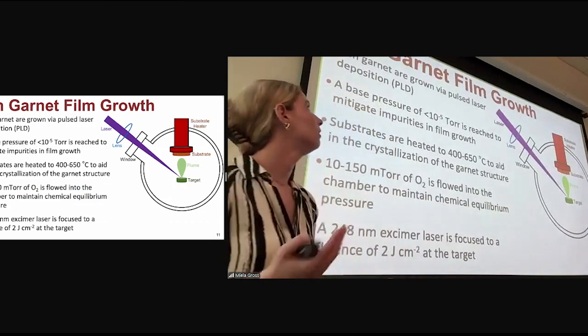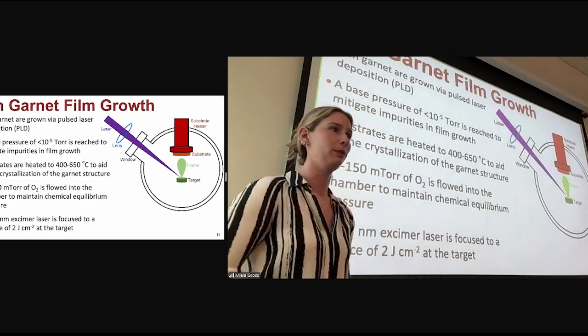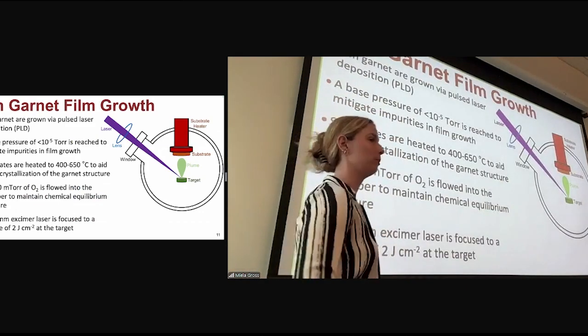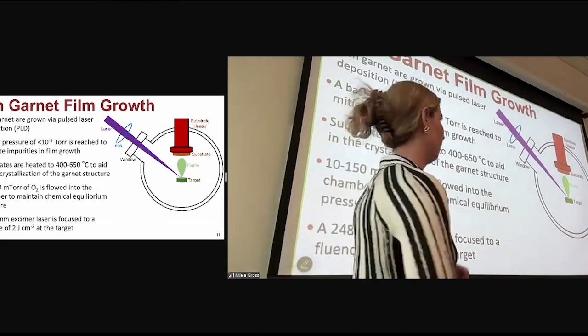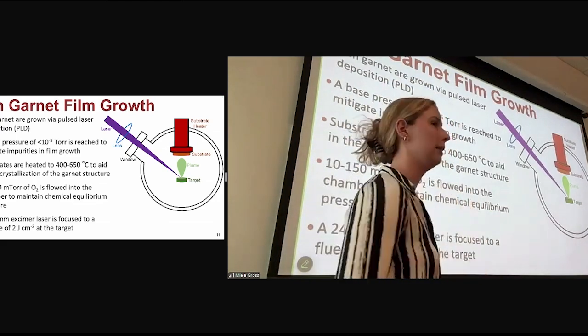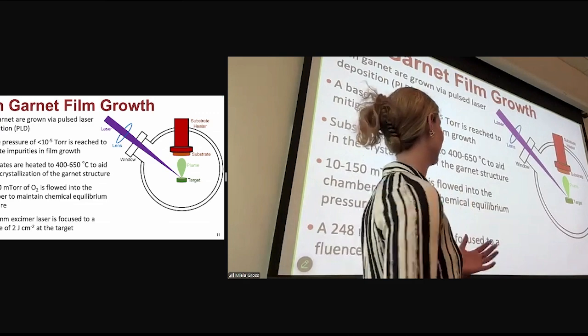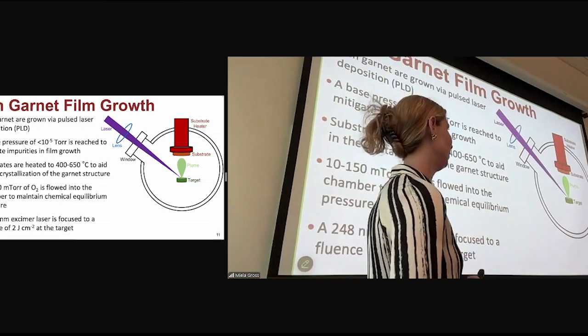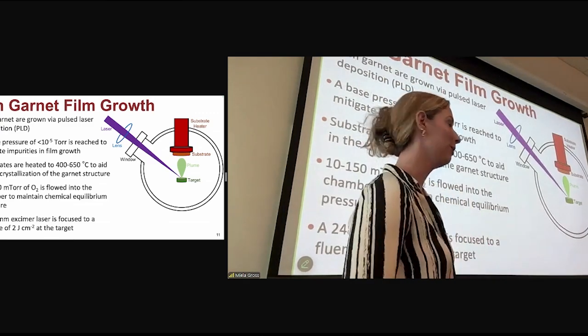So how do we grow iron garnet thin films? In this lab, we grow them through pulsed laser deposition, otherwise known as PLD. And pulsed laser deposition is a great method of growing complex oxides because it allows us to tune a lot of different parameters in the film growth.